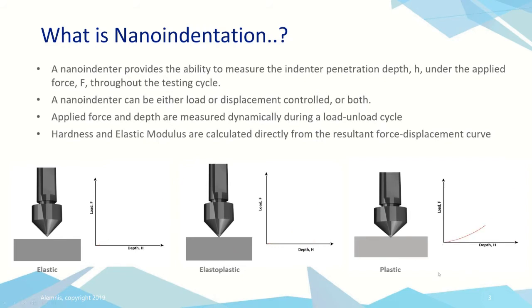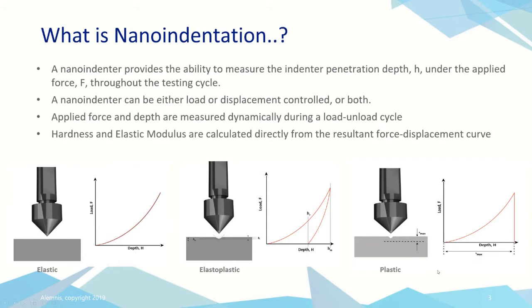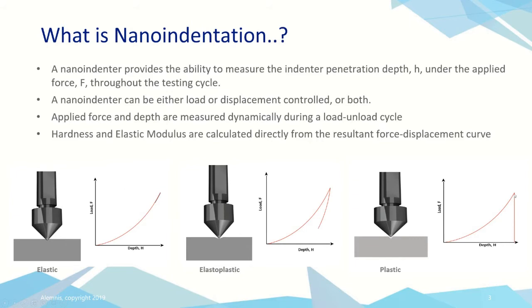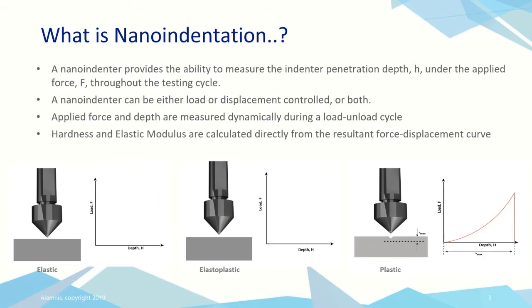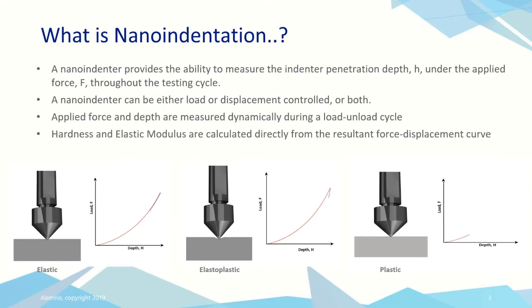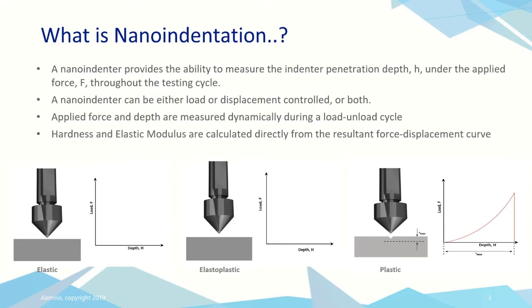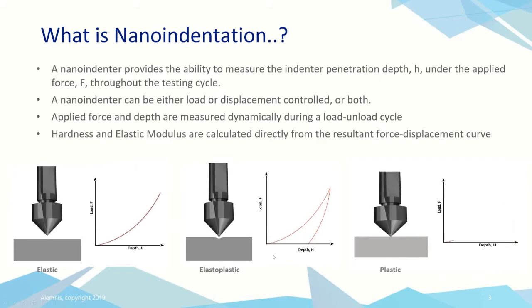On the right, we have a typically plastic material. So this could be a soft metal like aluminium or gold. And here we see that the unloading curve is almost vertical. So there's very little relaxation of the material when we remove the deformation. Now, these are the two extremes. Most materials fall into a mixed category where there's some plasticity and there's some elasticity. And we call this an elastoplastic response, as you can see in this middle example here.